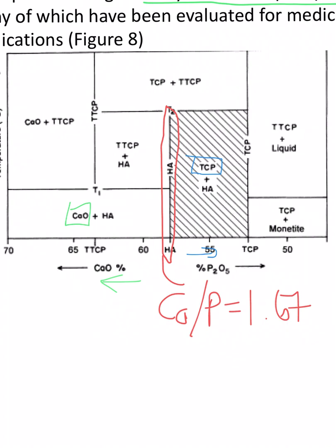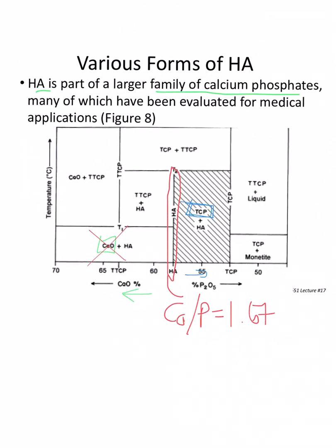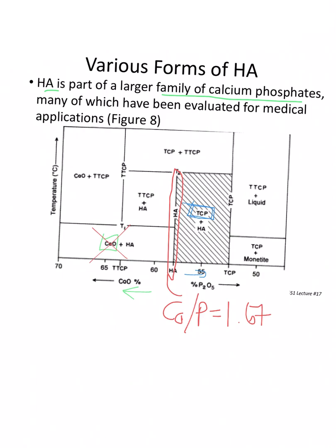And so if we're going to make an error, we definitely don't want to make the error of too much calcium. On the other hand, if we make the error of too much phosphorus, we make tricalcium phosphate, which, as it turns out, doesn't give you a pH of 12 and doesn't dissolve quickly. It breaks down. It's more bioactive than hydroxyapatite, so it's a good thing to have. All hydroxyapatite that I'm aware of is intentionally made with a slightly rich phosphorus content, because you can't hit that exact ratio very easily, but you can make it a little phosphorus rich and you're safe. Okay. So this is the lay of the land.